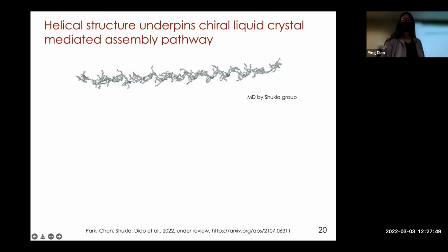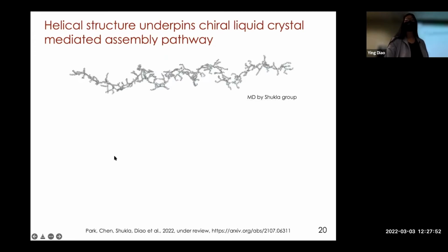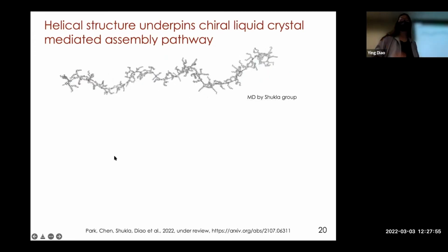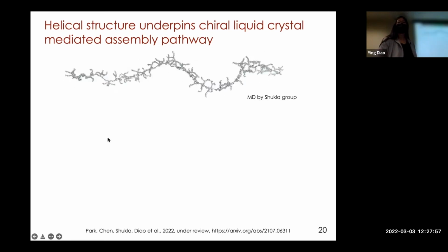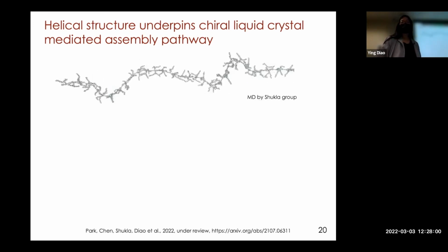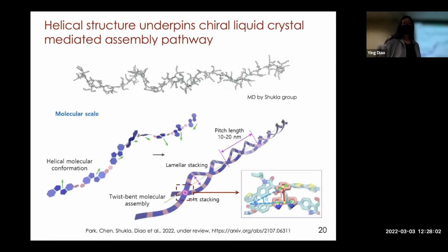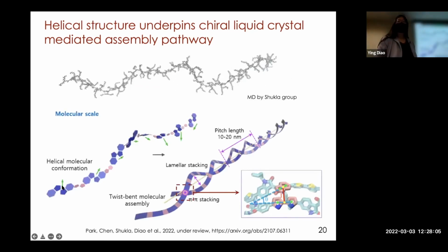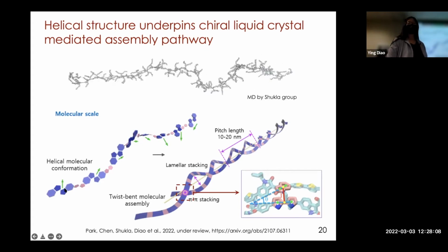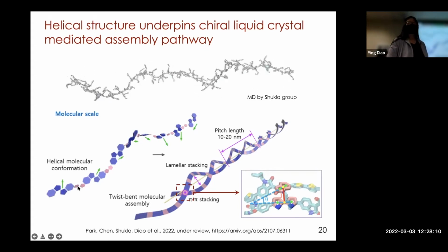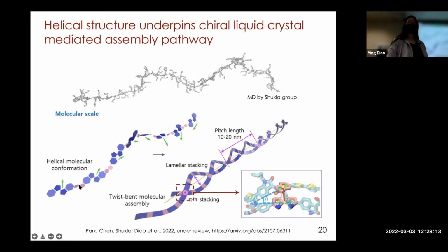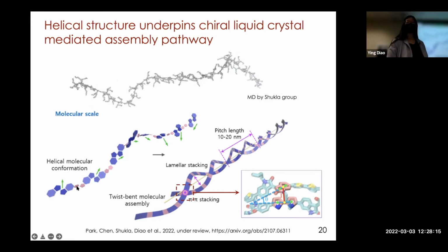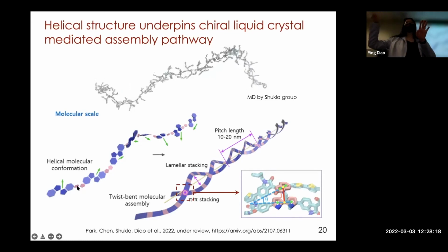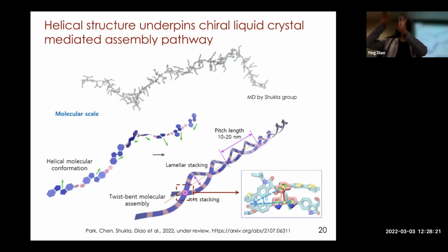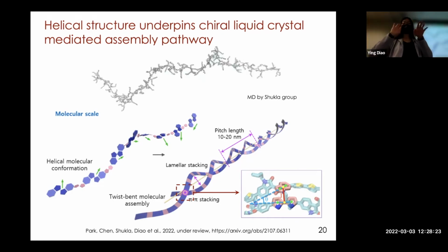We show that because the backbone of the polymer is slightly twisted, it can assemble in the solution phase as a helix, as shown by MD calculations. And we show that how the helix forms is because the dihedral angles are correlated. Basically, if you look at the dihedral between two furan rings, if it twists one way, the next furan dihedral will also twist the same way. So they want to twist in the same way. That's why they can form a helix over long range.